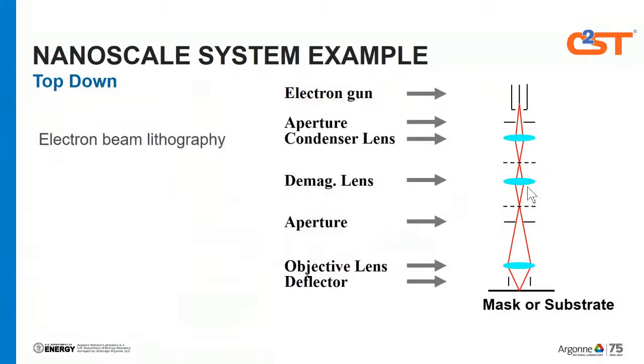We do this through electron beam lithography, which takes electrons emitted, focuses them through a couple of lenses, and then actually writes. The patterns are so small that visible light, which is on the order of hundreds of nanometers, won't work, so we have to use something much smaller. Electrons are that much smaller, so we can make these patterns at the nanometer scale.